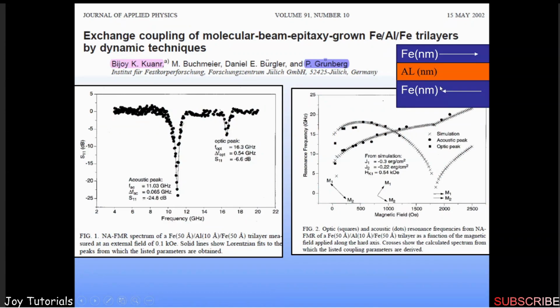aluminum iron layer. One can see the interlayer exchange coupling and hence the giant magnetoresistance through the ferromagnetic resonance of the acoustic mode. This is the in-phase precession of the magnetization vector of the two iron layers. When these two layers are in phase precession, one can have the deepest resonance, a kind of notch filter, that is the acoustic mode, and when they are anti-parallel to each other, or the out-of-phase precession, one can have an optic mode.